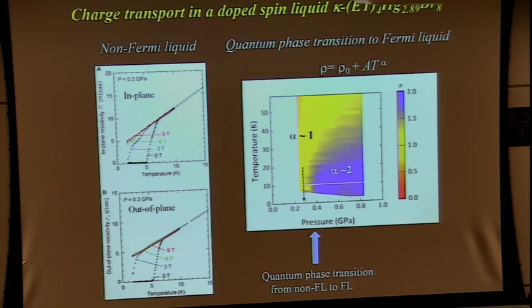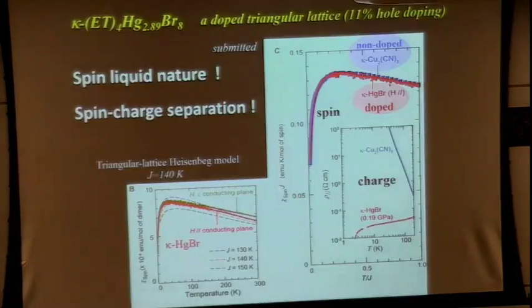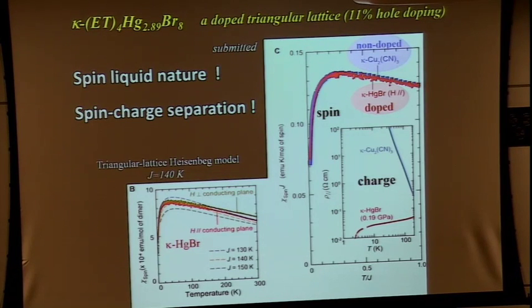So in the charge sector, the behavior is completely different. It's an insulator and a metal. However, in the spin sector, exactly the same, nearly exactly the same. This is a clear manifestation of spin-charge separation. So even in a metallic state, in the spin sector, spin behaves like a spin liquid. So that's why we say that we have a doped spin liquid.